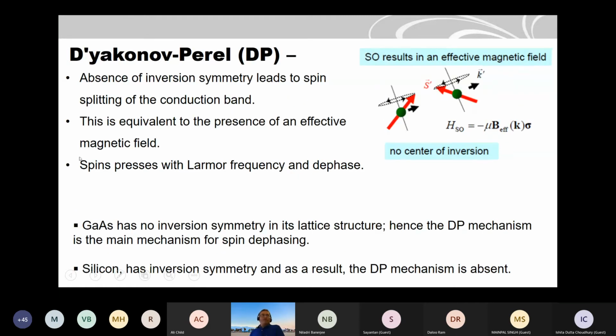Another mechanism is called the D'yakonov-Perel mechanism. Again, it was proposed for when you have a material which lacks inversion symmetry, for example gallium arsenide. So it's not a very symmetric material; inversion symmetry is not there in the crystal structure. When inversion symmetry is broken, it's like a polar material. You might have heard about different types of polar materials. So there is an internal electric field in those materials. This internal electric field together with spin orbit coupling creates a net magnetic field.